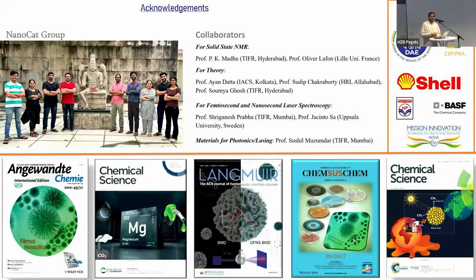He says, curious to know how porous was the sample? If not, do you think porosity could have an effect on plasmonic activity? The sample was porous because I showed you the DFNS. It has very unique porosity because of the fibrous nature. The surface area can go up to 800 meters squared per gram. When we loaded the gold particles onto the silica surface, obviously the porosity will go down, but it was still porous, I think around 300 meters squared per gram. Whether the porosity of the silica has a role in plasmonic catalysis, we haven't studied that, but possible.